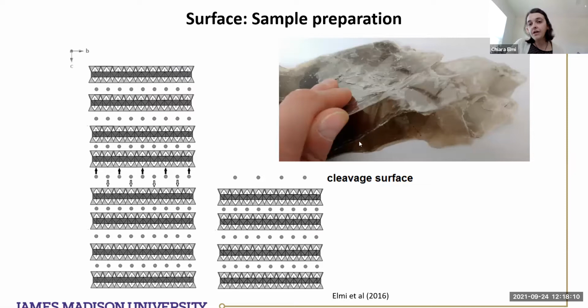Okay, if you see in this picture what I said before, at the macro scale the mica is forming layers. So any time that I create a clean surface to study the crystal chemistry, I cleave the mica along the interlayer. So mostly what I'm doing is splitting the layers on one side and another. Any time that you have a mica, I know that the temptation is to split the layers, and I'm sure that your professor said don't split a mica, but I did that for years for studies, so it's okay, I can say. For this kind of study, we study the surface.